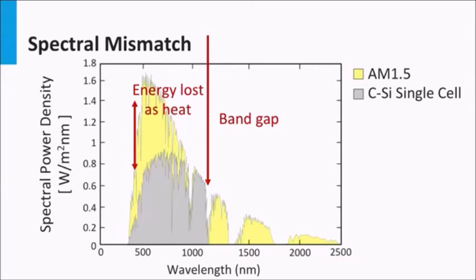The electrons are excited to a level higher up in the conduction band and the holes down to a lower level in the valence band. They will quickly relax back to the edges of both bands. The rest energy is released in terms of heat. The gray area represents the total amount of energy in the solar spectrum which is used to excite the charge carriers. The yellow area above the band gap represents the energy which is lost as heat.